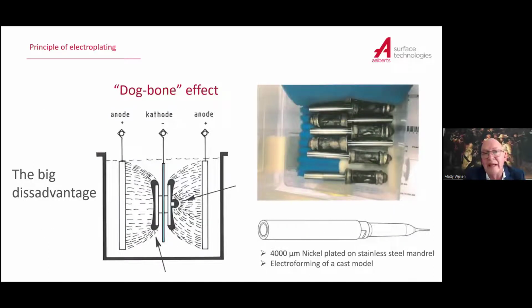Electroplating has one big disadvantage, and that's called the dog bone effect. It has to do with the following. If you look at the part which you have on a cathode, and you see it has a little bit of an H-shaped part, it's the white thing. Then you put that current on it, and what happens is that you get current lines from the anodes, plus, to the cathode.